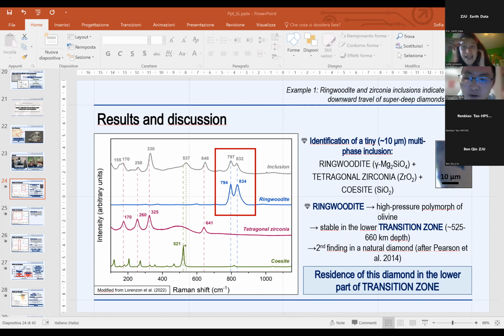At this moment, we were not able to determine the age of this diamond, even if there is a zirconia phase, because for this kind of determination we must extract the inclusion for the analysis. Considering that this inclusion is extremely tiny, we prefer not to try to extract it, because probably we would lose the inclusion.